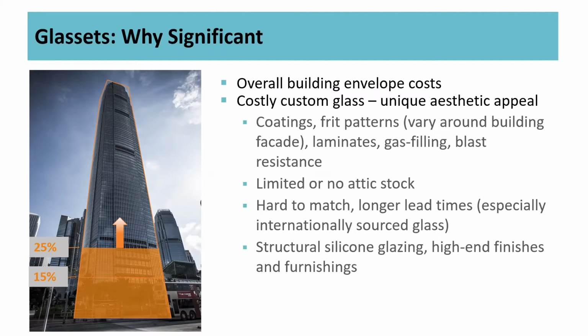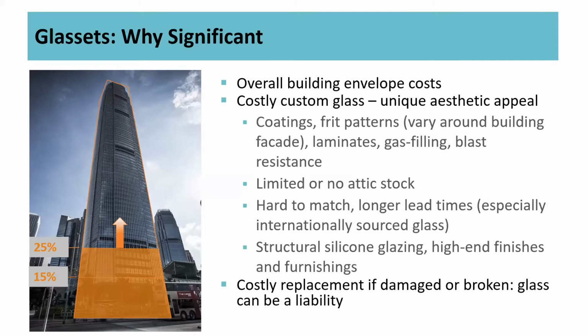And what we're finding out is that on most projects, except for maybe a few recently that I've seen sourced from China, there's limited or no attic stock provided at the end of the project that you could utilize to replace any glass that might be blemished or damaged. The glass itself, because of the reasons noted, becomes harder to match, with longer lead times, especially when sourced internationally. And then the ubiquitous use of unitized systems with structural silicone glazing and maybe some nearby high-end finishes on the inside can make it very costly to replace any glass. So glass not only becomes an asset, but it also can become a liability.